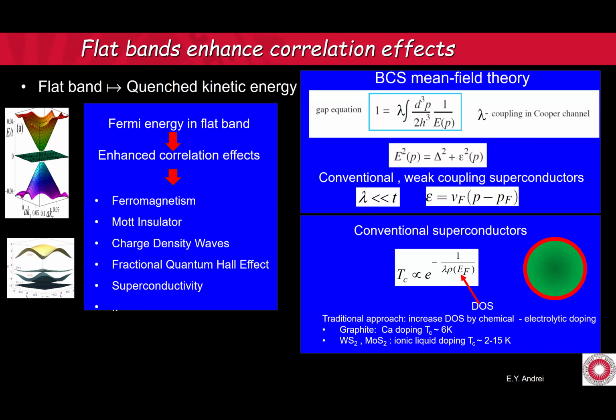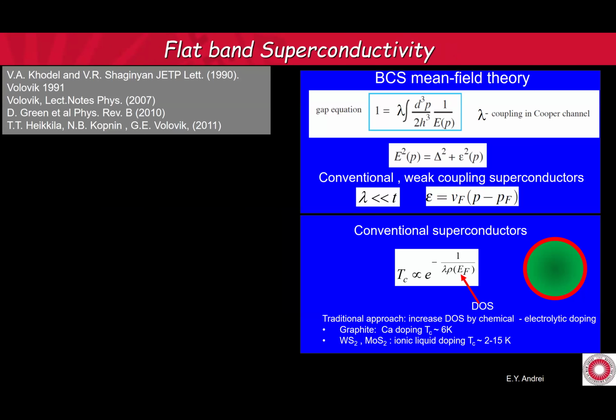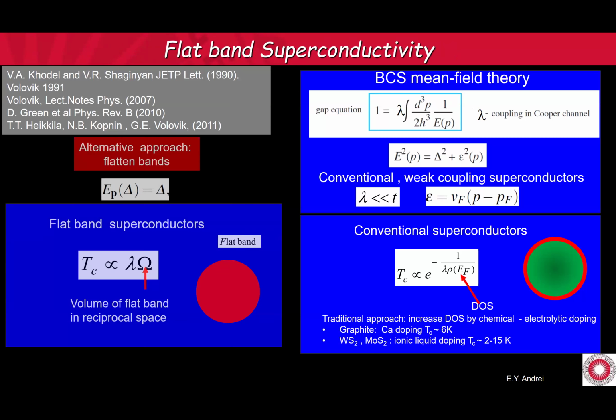So about 3 decades ago, in the 90s, there was this group of Russian expatriate theorists who worked in Finland, and they came up with this very intriguing idea. They said, okay, what if this epsilon here is completely zero? So basically, you have no dispersion in the excitations, you have a flat band, and this integral becomes very simple. And lo and behold, you get the TC, rather than being exponentially suppressed in the coupling, it is linear in the coupling. And omega here is the volume of the flat band in reciprocal space.